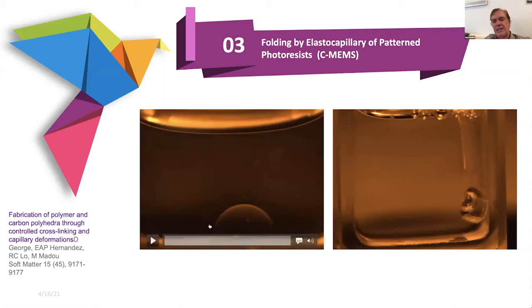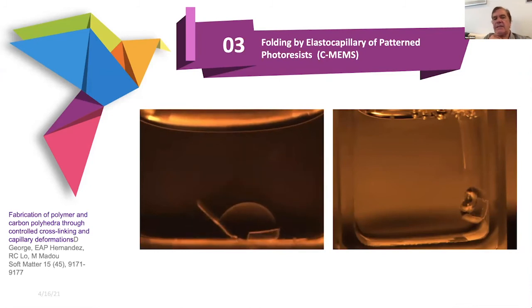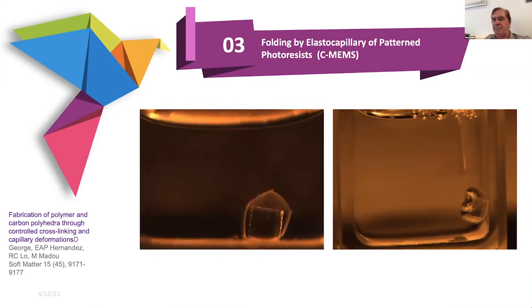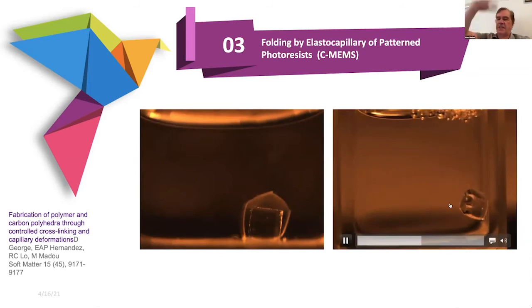Here, the droplet is sitting on a polymer sheet. And here we go. You can see the polymer faces self-assembling around the polymer droplet. You can see we chose the droplet a little bit too large here, and it couldn't completely capture the droplet. Over here, we have the droplet by heating coming out of the cube. You can see the droplet escaping here. One of the faces lifts off and the droplet can come out of it.